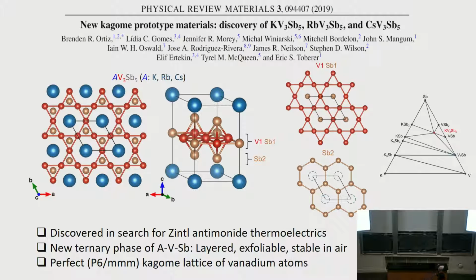So how was this material discovered? I have them here, vanadium-based, three of them because you can change the alkali metals. The vanadium forms this perfect Kagome lattice in the plane. You have antimony here to make it stable. Then the antimony is also above and below these triangles. They form their own honeycomb lattice, and then are sandwiched by alkali metals.